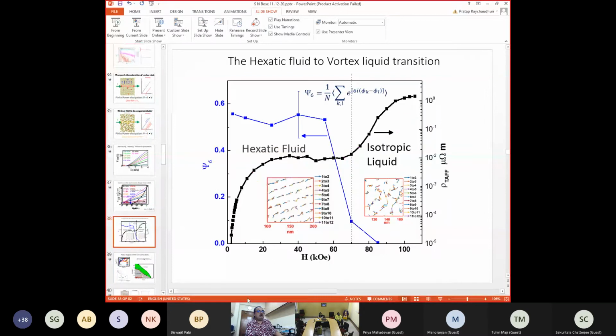I can continue measuring this slope up to higher currents, and what I will see is this. In the hexatic, I have this resistance at very small current, which is saturating. But then when I enter the isotropic liquid, this resistance again increases rapidly. Why does it increase? That's because in the hexatic fluid, the vortices can flow only in preferential directions. But now when it enters the isotropic liquid, it can move in all directions freely. So I have a large increase in the effective mobility.